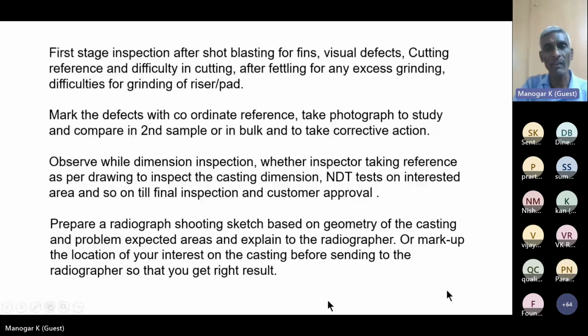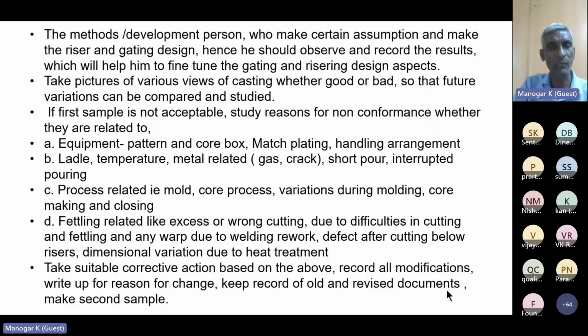And the method person should be aware of NDT reading, how to interpret the film. Many times what happens, the NDT person gives a report for gas or shrinkage as a crack, or a crack as gas or shrinkage. And the shooting sketch also you have to be careful about and see how he is shooting the casting. The RT film view should be evaluated, whether there is any expansion of the view or contraction of the view compared to the casting size, which will change the level of the defect.